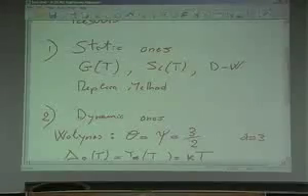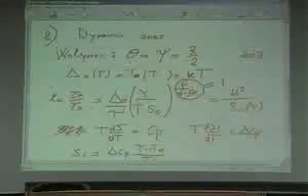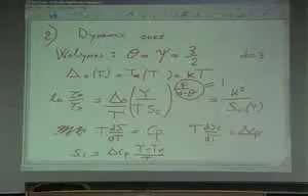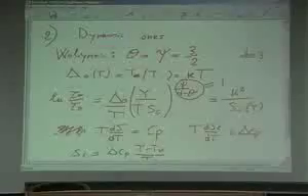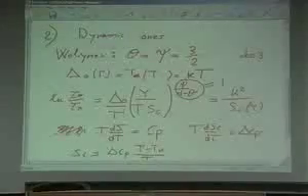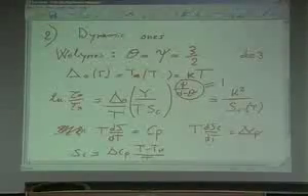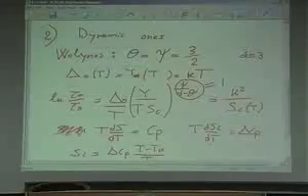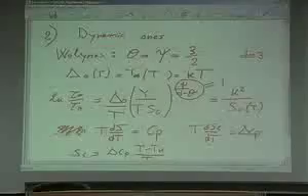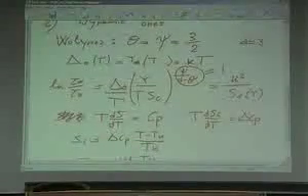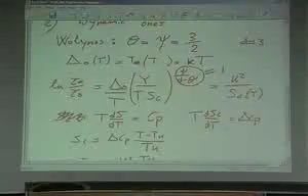The other point is in the dynamics: the 1 over Sc prediction is not Adam-Gibbs, right? There is a T which is missing. And I think Adam-Gibbs works better, though I'm not 100% sure. And going from there to the Vogel-Fulcher form, you assume that delta Cp is constant.